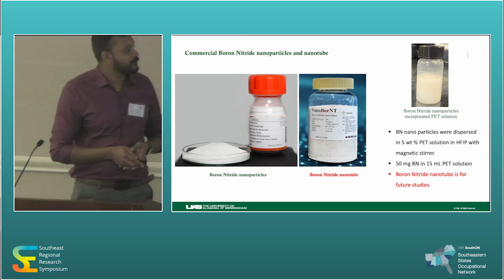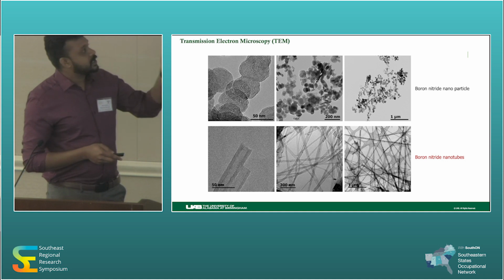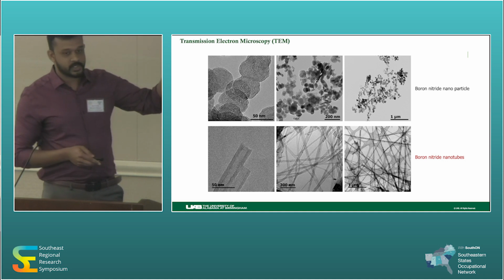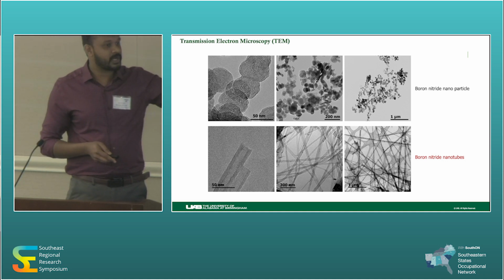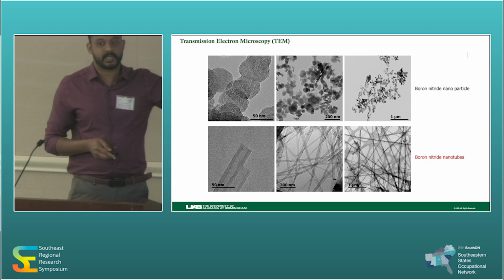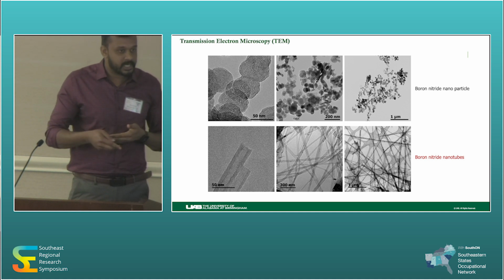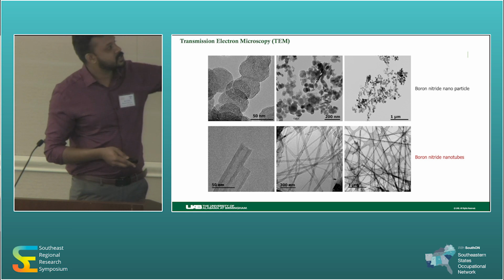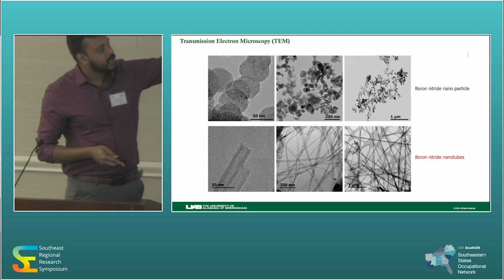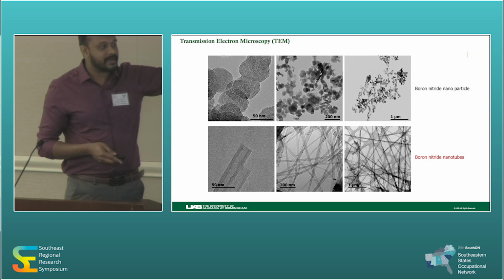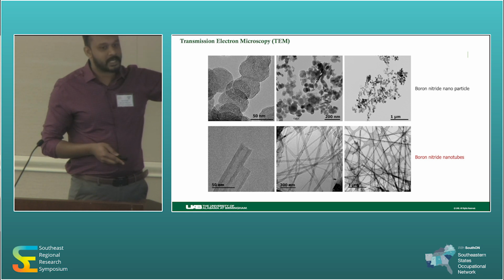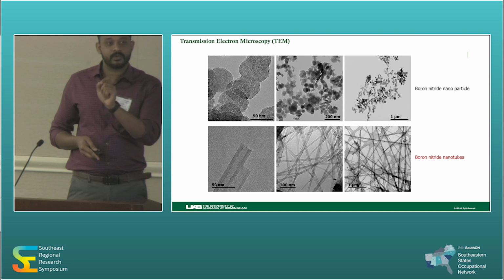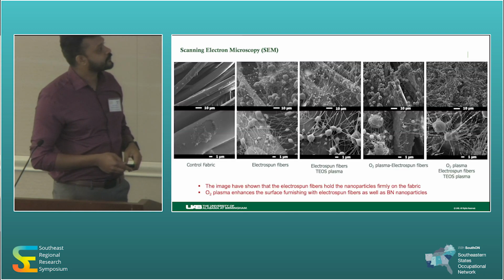That's the entire thing. Then this is a transmission electron microscopic image of what we have, the boron nitride nanoparticle as well as boron nitride nanotube. The nanotube study is going to be pursued. From the image itself, the boron nitride nanoparticle has a dimension of almost 50 nanometers, and the boron nitride nanotube has a diameter of around 25 nanometers.